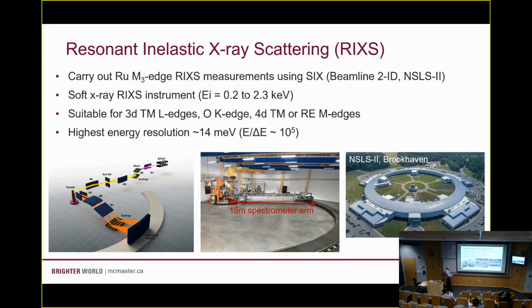And so what we're doing here are resonant inelastic X-ray scattering measurements. The resonant part just tells us that we're tuning the incident energy of our X-ray beam to an atomic absorption edge associated with one of the elements in our sample. In this case, ruthenium. We're going to go to a particular edge, this M3 edge, and this ends up being a soft X-ray energy. And so there's only one beamline in North America where we can do that. That's SIX at NSLS-II. Okay? So this is an instrument that is great for these low energy inelastic X-ray scattering measurements. What kind of experiments you can do really depends on what elements are in your samples.